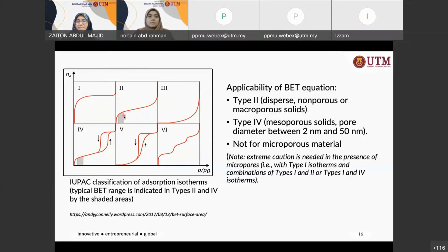The classical BET range is between 0.05 to 0.3 relative pressure. So you have a plot here, P over P naught, this is the relative pressure. The maximum P over P naught is about 1, 0.99 or about 1. And this is the number of moles adsorbed or the volume. You can have it in terms of number of moles or in terms of volume. So this is the BET range in which the BET model is applicable. And it is strictly not for microporous material. So in this case, you might not get a purely type 2 or purely type 4. You might get a combination of type 1 and type 2 isotherm, or type 1 and type 4 isotherm. So be very cautious of the presence of micropores.